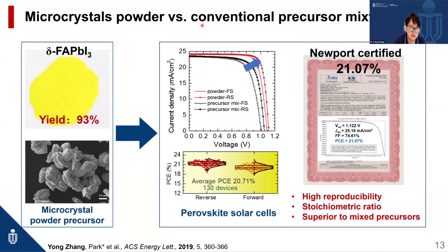We compare this kind of microcrystal powder precursor with the conventional precursor mixture. In this work, we optimized the reaction condition to get a high yield of 93% delta phase of FAPbI3.